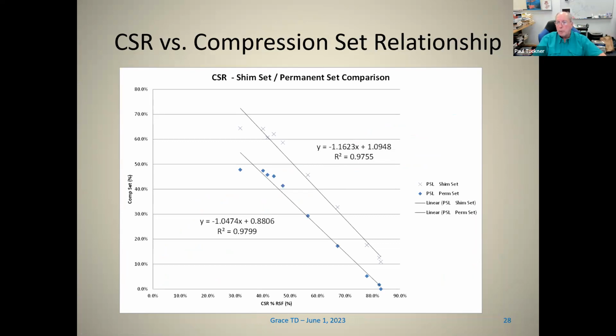It shows that when your shim set is 100%, it coincides with 0 sealing force. So being able to have both of these gives you some information on what's happening. And sometimes if the degradation is not uniform, it skews some of these values.